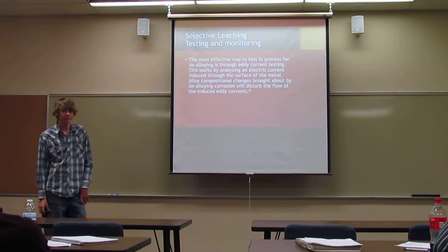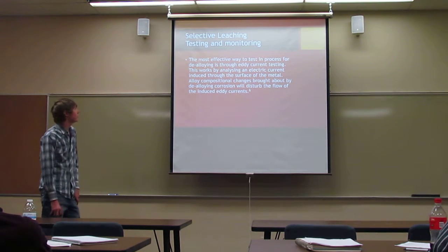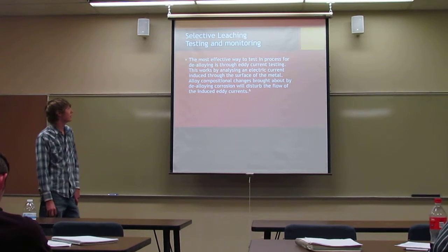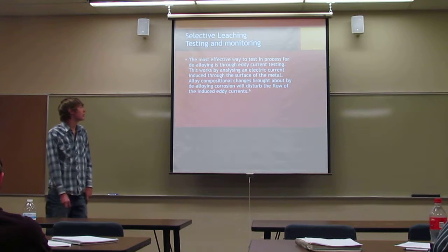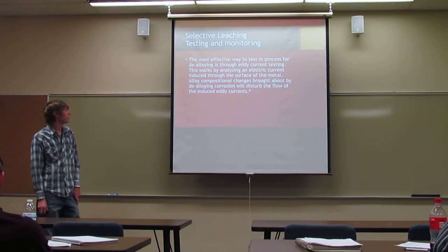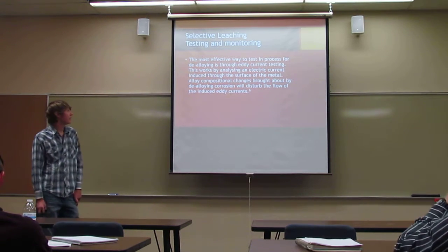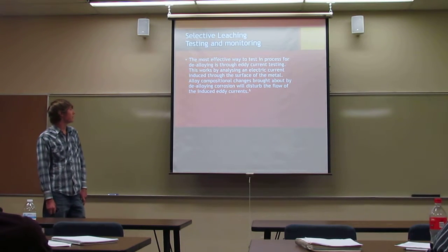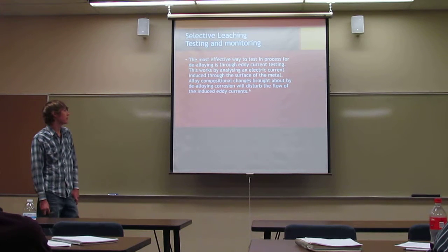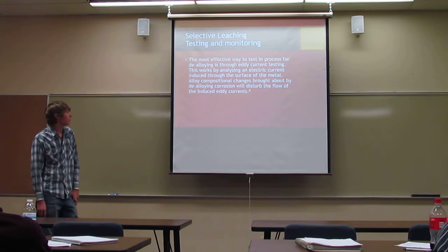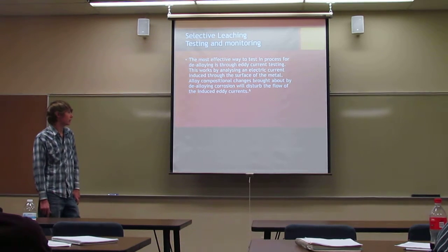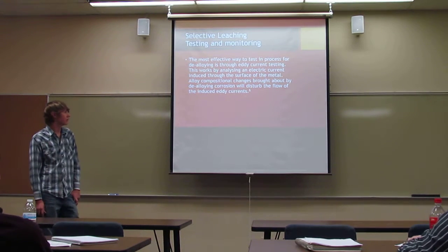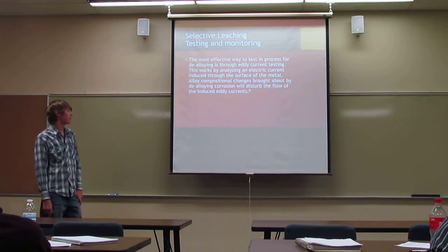Testing and monitoring. The most efficient way to test in process for dealloying is through eddy current testing. This works by analyzing an electric current induced through the surface of the metal. Alloy compositional changes brought about by dealloying corrosion will disturb the flow of the induced eddy currents.